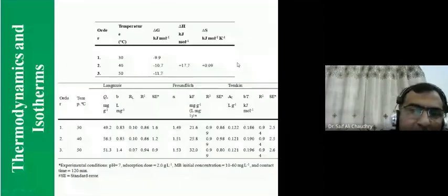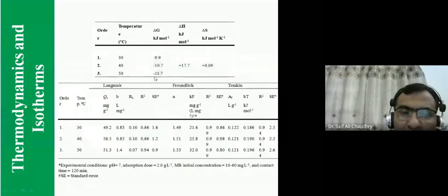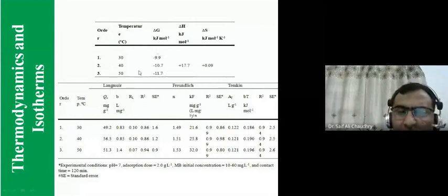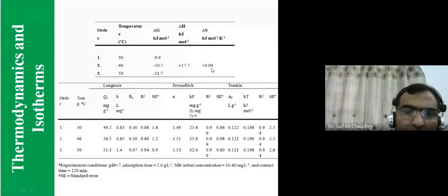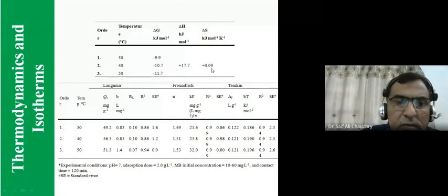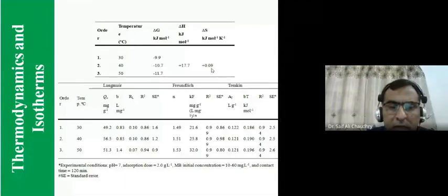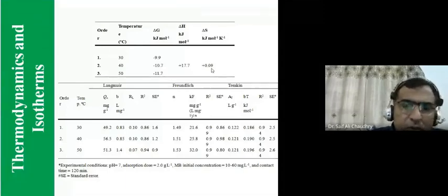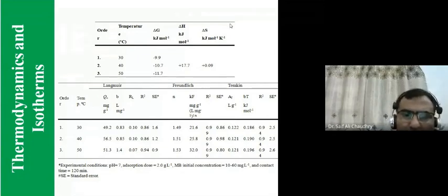Again, we have delta G values of 9.9, 10.7, and 11.7. Again, it is an endothermic reaction, and the feasibility of the adsorption is higher as compared to the previously used compounds. And the delta H value is 17.7. Again, the delta S value is 0.09, indicating the mechanism where hydrogen is replaced by the dye molecules or any pollutant molecules. Therefore, this delta S value is coming positive.